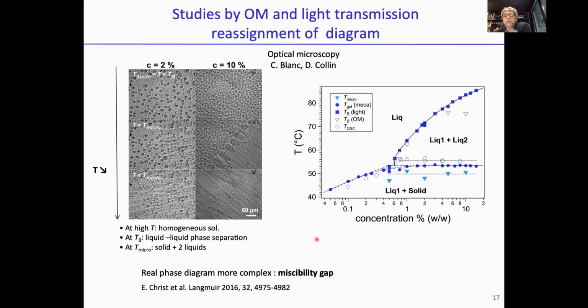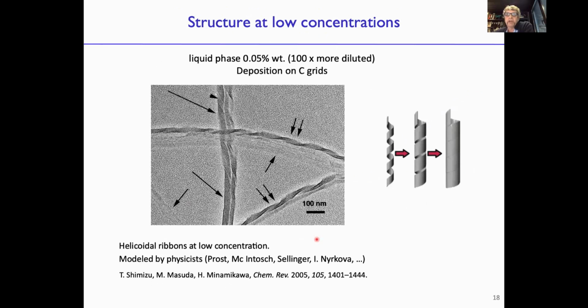So by these studies, we were able to show that for large concentration, it is very normal that we get two kinds of objects, and that it's not an artifact. So supercritical drying affords a real picture and the real distribution of our gelators. And it's really important for many applications, such as catalysts. I will show you at the end some of these applications.